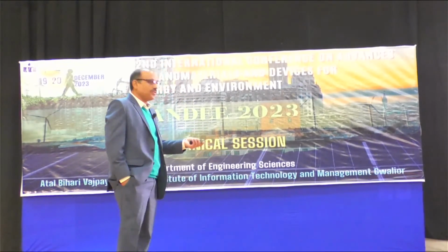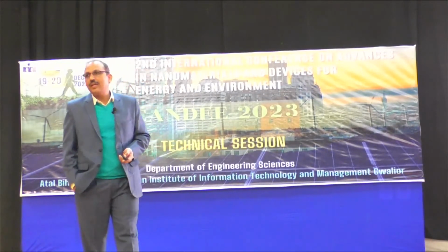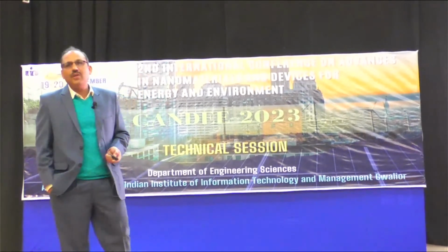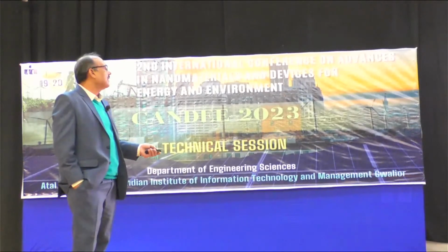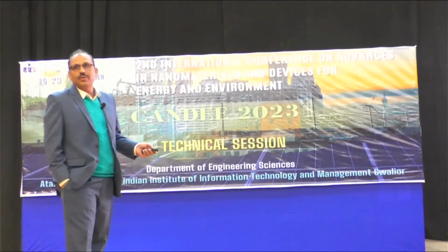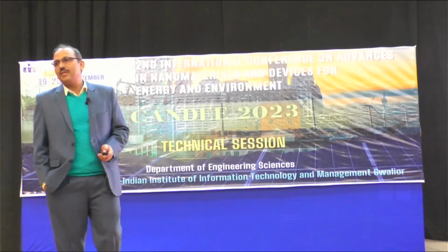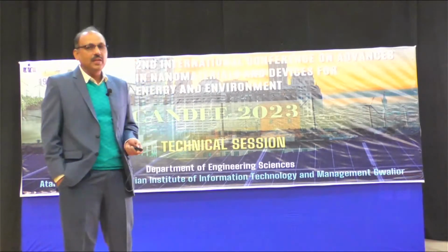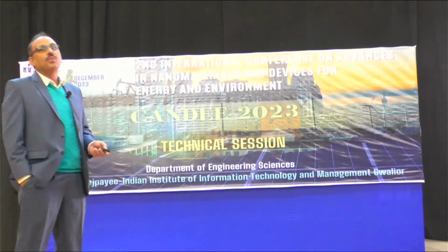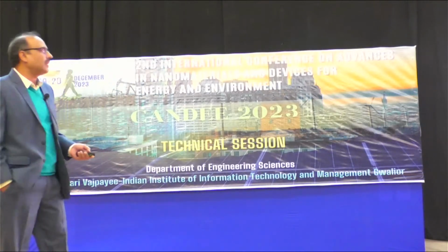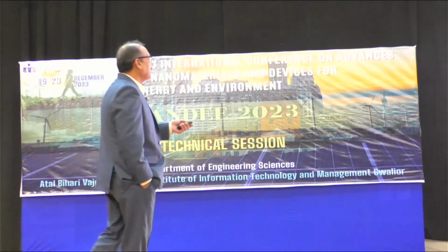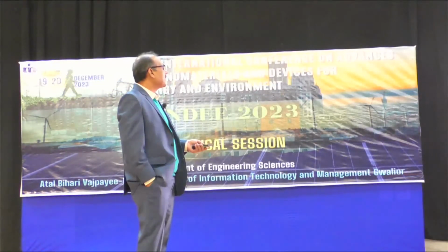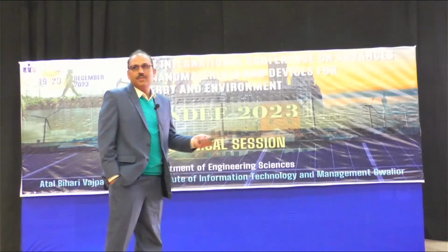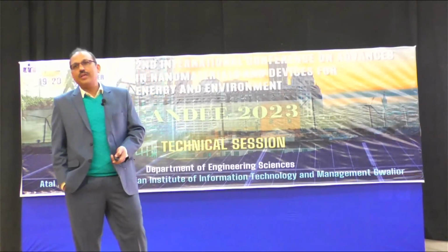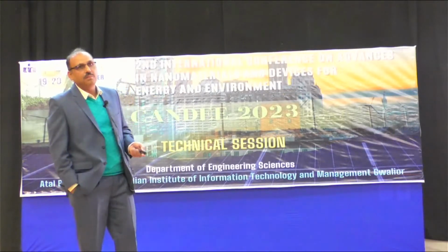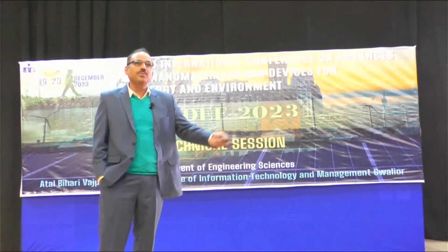This is what I used for XRD, and with Rietveld refinement we found that the volume of our system increases when we dope 10 atomic weight percent magnesium. We especially focus on only 10% for hydrogenation and other properties. You can see here the TEM and HRTEM, and that system is easily available for all the students. You can go and take the photographs and discuss with your supervisor.